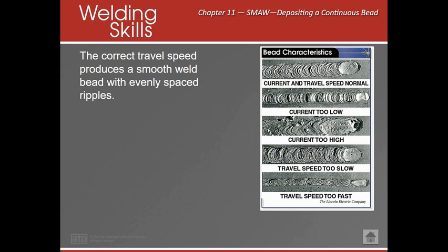And then the last one we have here is our travel speed too fast. If you're welding and your travel speed is this speed down here, you're doing a couple of things. Number one, your bead size is not the correct size. Number two, you're going too fast, and you're not putting any reinforcement into that joint. You're going to get excess undercut on the toes of your weld, and that weld is not going to do anything. It's literally just sitting right on top of that weld.